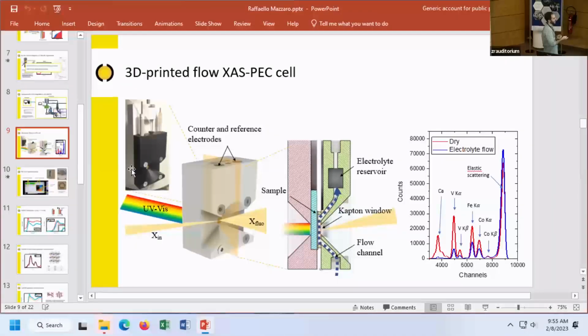So to do that, we designed everything to be in flow, and we introduced the three-electrode system in our photoelectrochemical cell. And you see here that the resulting fluorescence spectra in dry conditions and the one during the electrolyte flow are pretty much similar, in particular in the case of the elements we're interested in, so iron and cobalt in particular. We have a drop, obviously, because the electrolyte is absorbing some photons, but the drop is about 40%, so it's not really a large drop, and it's pretty good for this kind of analysis.